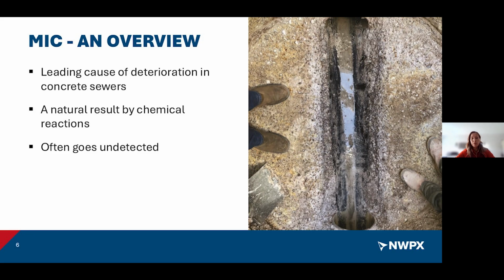This particular photo on this slide is out of St. George. When you first look at it, you may see nothing wrong with it, but it's very important to recognize how microbial-induced corrosion looks. For this one, you can see the pebbly structure, right? When concrete manholes, the troughs and benches are poured, typically the bench area is very smooth, and you should not see the aggregates. For this one, there is some microbial-induced corrosion happening, and you can see that pebbly structure.